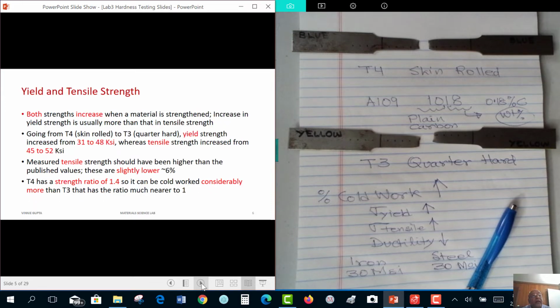Let's look at yield and tensile strength. Now, both strengths increase when a material is strengthened. We just spoke about this. Increase in yield strength is usually more than tensile strength. We saw that yield strength increased by almost 50%, whereas tensile strength increased only about 10% or so. So we went from 31 to 48, whereas tensile, we went from 45 to 52.